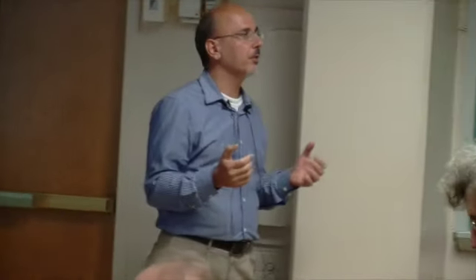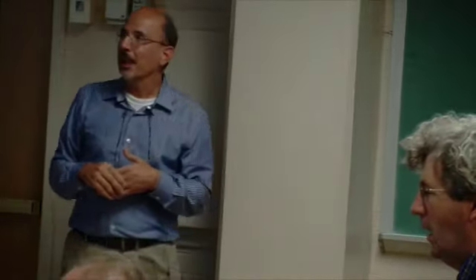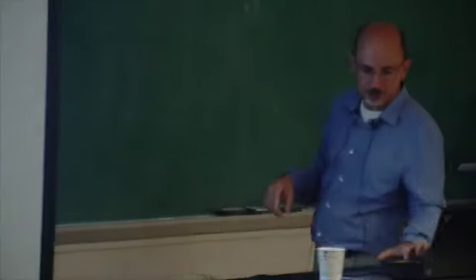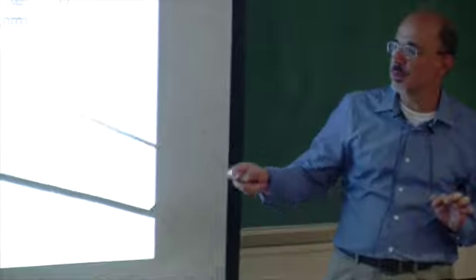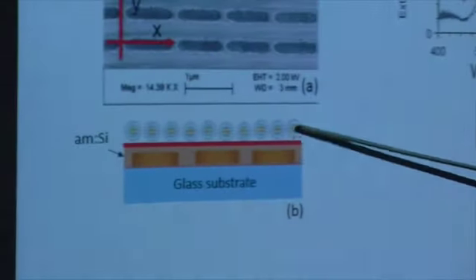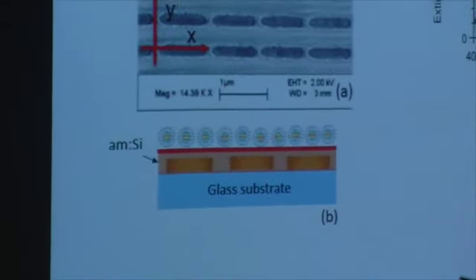Quantum dot itself, in the absence of any metallic nanoparticle, is not polarized. It has kind of spherical symmetry, it is not a quantum rod or anything, so there is no preferred polarization for it, and this shows that. Now, look at the emission of the quantum dot on the top, when there is a metallic nanoparticle underneath.